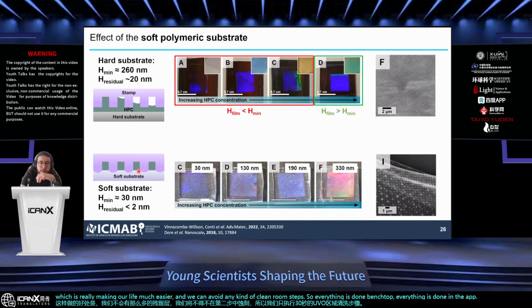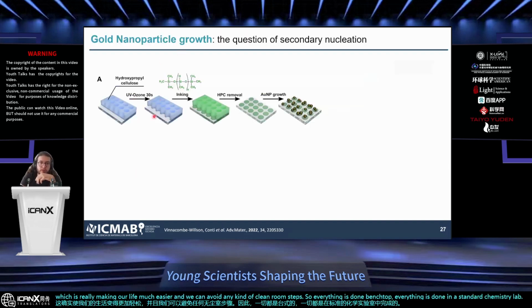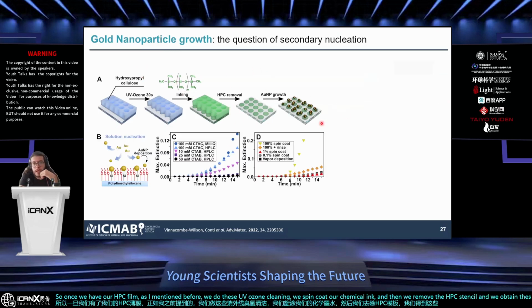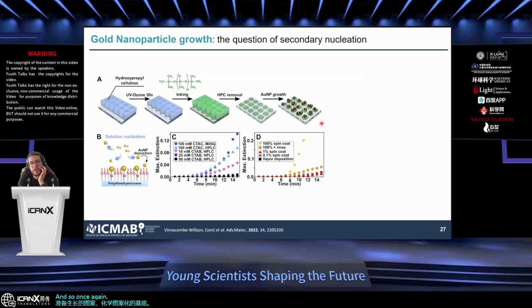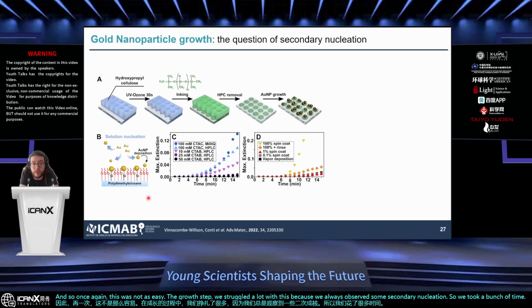So once we have our HPC film, as I mentioned before, we do this UV ozone cleaning, we spin coat our chemical ink, and then we remove the HPC stencil and we obtain this chemically patterned substrate that is ready for growth. And once again, this was not as easy. The growth step, we struggled a lot with this because we always observed some secondary nucleation. So we took a bunch of time optimizing our growth solution in order to avoid the secondary nucleation.